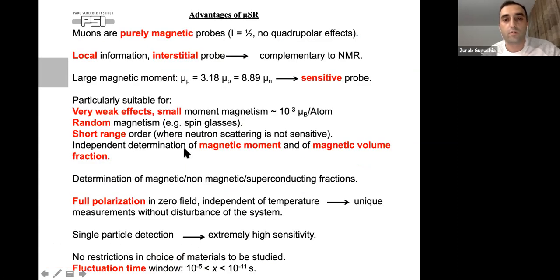There are many advantages of muSR, but what we used in these topological magnets is that it is very sensitive to small moment magnetism. You can measure a moment as small as 10 to the minus 3 Bohr magneton, and you can measure short range magnetic ordering. So we can determine moment and volume fraction separately. And the fluctuation time is also complementary to neutron scattering. Something that can be fluctuating for neutrons is static for the muon, so we can look at slow magnetic fluctuations. And we don't need to polarize the muon spin, we don't need any applied field, so we can just do measurements in true zero field.